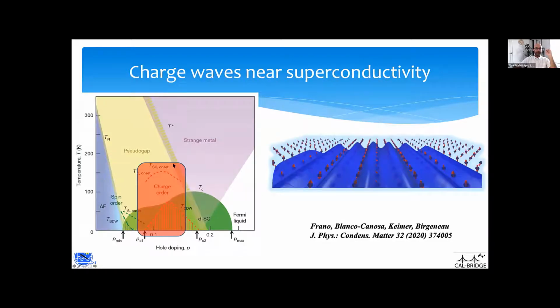In addition, in this region right here, what happens is that not only do you have spin stuff going on, this arrow stuff, but you also have what's called the charge density wave, or charge order, which is basically a wave that forms in the electronic charge. So the electronic charge, as you know it, you probably remember it being a discrete thing, like the electronic charge is E, right? But it turns out that in these materials, it can form a wave. The electric charge forms a wave. In fact, and this is something that I've spent a lot of my research on, looking at this charge density wave, or charge order, or charge wave, as I described here. And I'm going to talk to you a little bit about that.